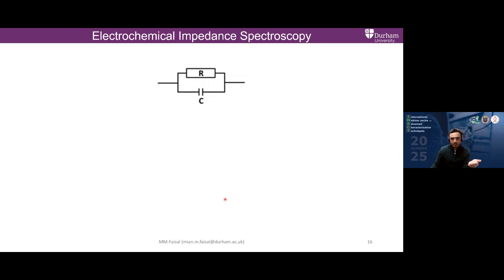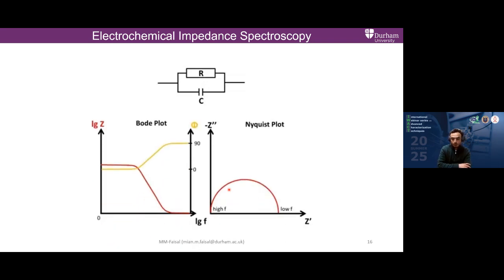When you combine resistor and capacitor in parallel, everything changes, because in the previous case the trend was parallel to the y-axis, and even if we connected a resistor, there was just a displacement of the trend. But if the resistor is connected with the capacitor in parallel, that's how it differs, and you now get a proper semicircle formation. Why is that so? Because when you connect them in parallel, it depends on the value of the frequency. At certain frequencies the capacitor will block the current, and most of the current will go through the resistor, and at other frequencies current will go through the capacitor, and that's how you get a semicircle formation.